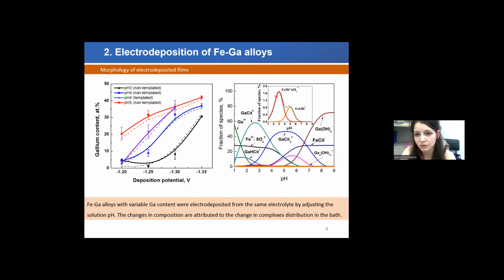Also, we can see that in this region, there is a decrease in the sum concentration of iron hydroxyl complex and iron complex with the citrate. Citric acid here was used as a complexing reagent. So all this together supports the idea that gallium will be preferentially incorporated at the higher pH. Interestingly, what we can observe from this graph also is that when we perform electrodeposition on the templated substrate, so the substrate with the polystyrene spheres, the films have a higher gallium content as compared to the non-templated substrate.